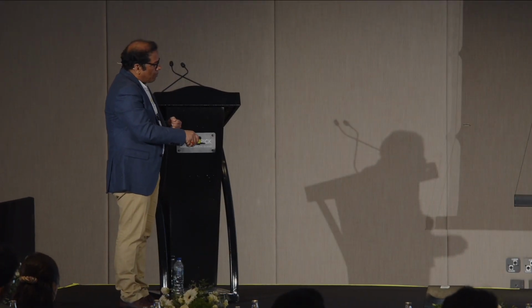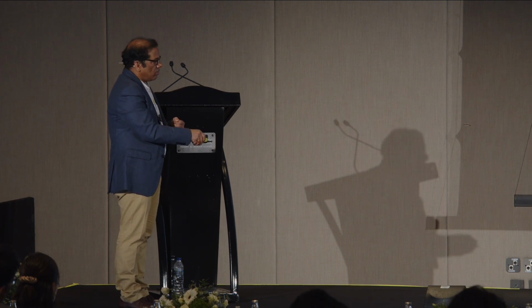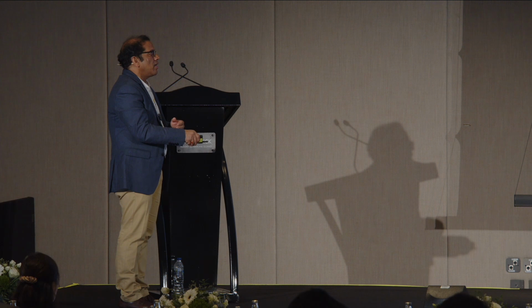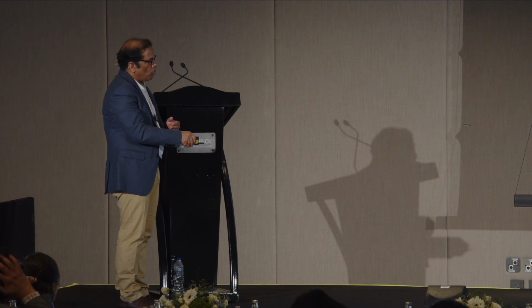But when we added a little platinum, there was an enormous rate increase to 14.72 millimole per gram per hour, with CH4 around 290 micromole per gram per hour, and selectivity of 97%.